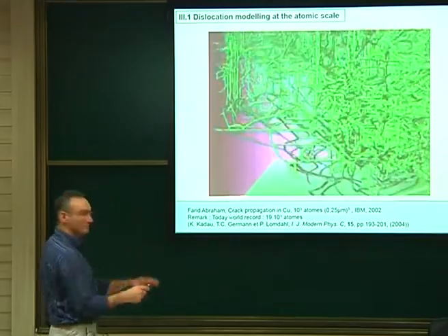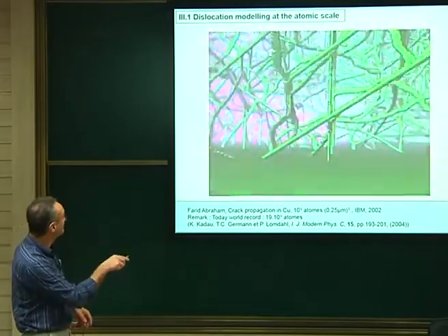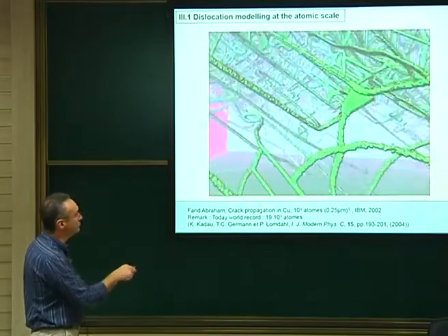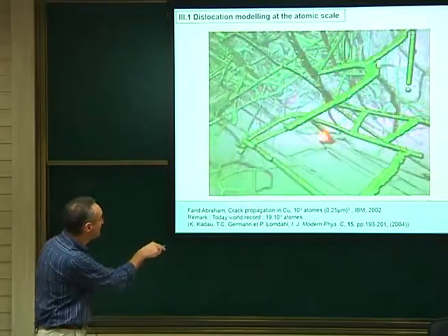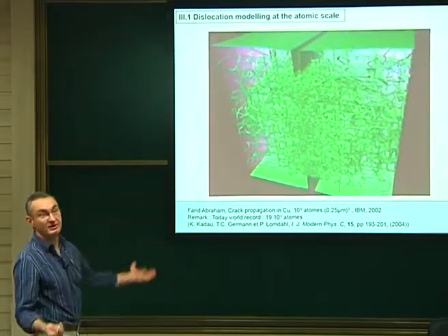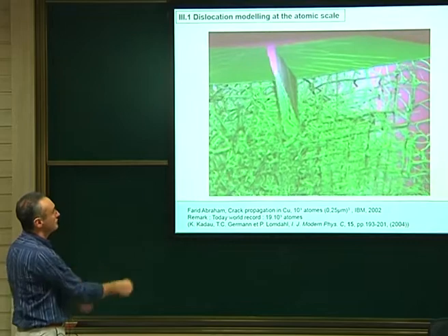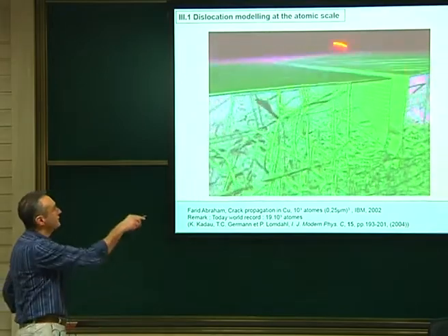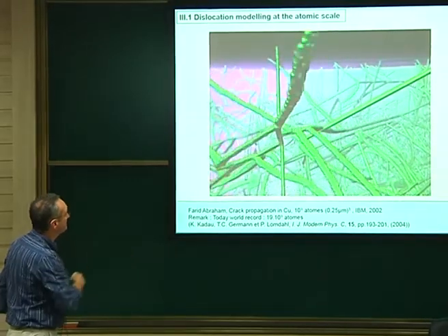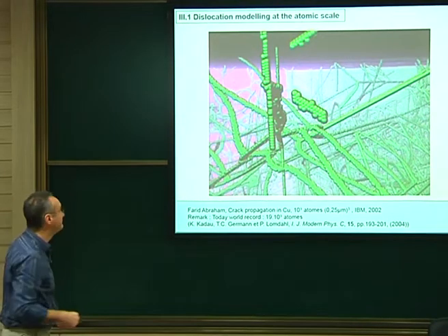It's always moving, so I hope you are not sick looking at that, but you see some dislocation junctions. Sometimes you will see some interstitials, some small dislocations moving away. It could be loops, prismatic loops or interstitials. You have some tetrahedra formed here. This kind of structure is a direct output of the MD simulations. You can see steps at the surface, plastic steps, where the dislocation came out. It gives a kind of roughness at the surface. You can see the junction here, another junction built there also. Stacking faults, small stacking faults. All these things, okay?